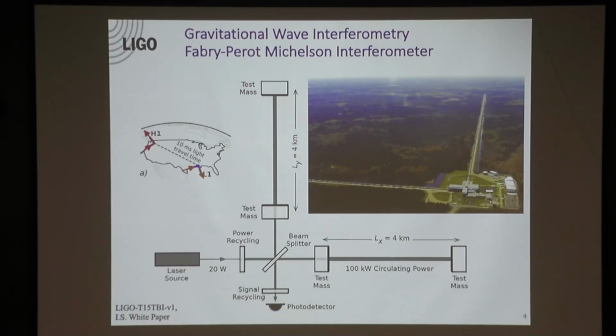So if you think about that, 100 kilowatts of circulating power, what are you going to use for the mirror? In particular, you are not going to use a piece of metal, because the absorption in a piece of metal at 100 kilowatts, I mean, it would be vaporized instantly. It would be vaporized long before we even got to 100 kilowatts of circulating power. So you cannot use a metal for a mirror. So what you use instead is a Bragg reflector. It's essentially a quarter wavelength system with a multi-layer of a high index layer and a low index layer. And each of them are perfectly transparent and not absorbing at all. So you have to have less than parts per million of absorption.